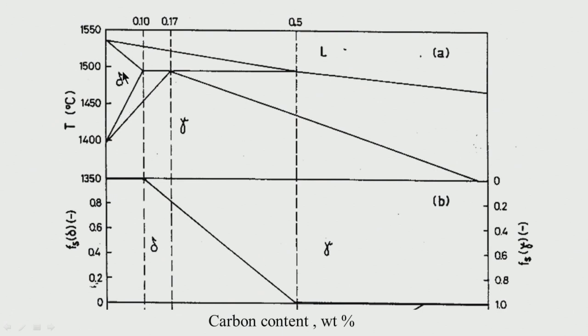So, during solidification we have only delta, and only at lower temperature during cooling we have gamma, and delta to gamma is taking place relatively high, because with low carbon everything is relatively high. So, solidification is taking place through delta, and delta remains for quite some time depending on the carbon. As you have very low carbon, delta comes down to quite low temperature, then only it transforms to gamma. Here this is delta plus gamma, and this is finally gamma.